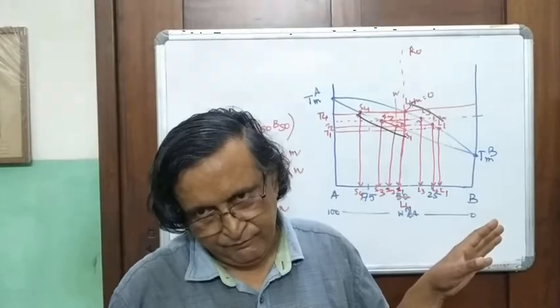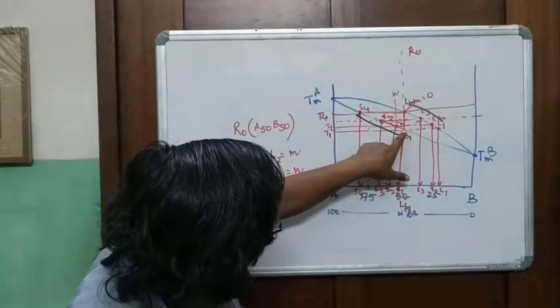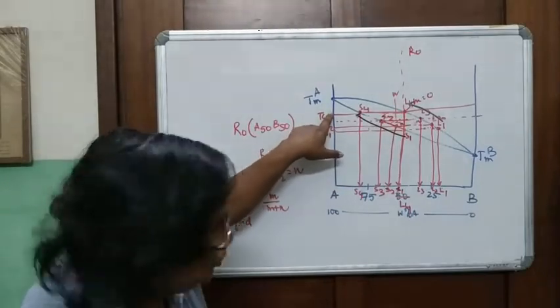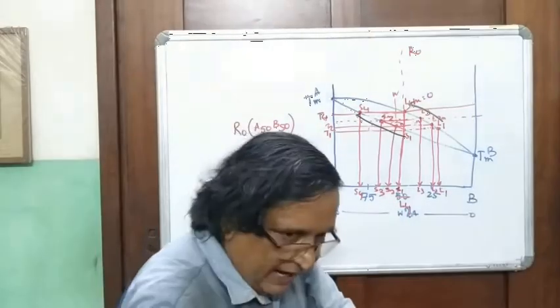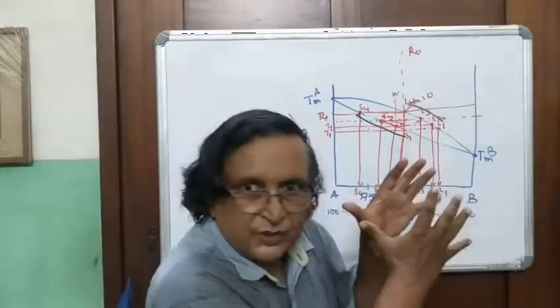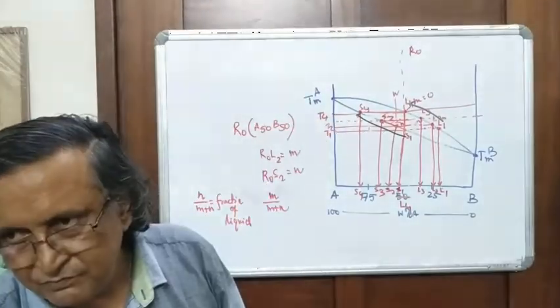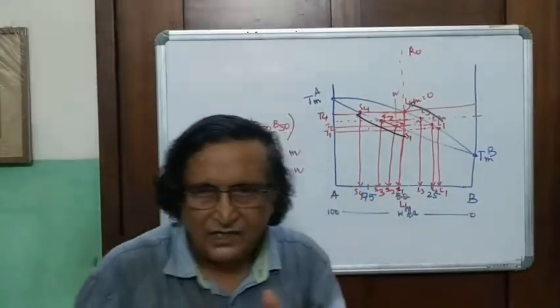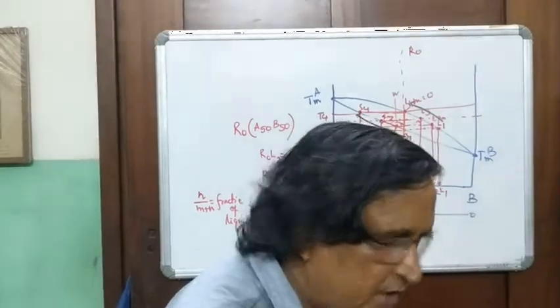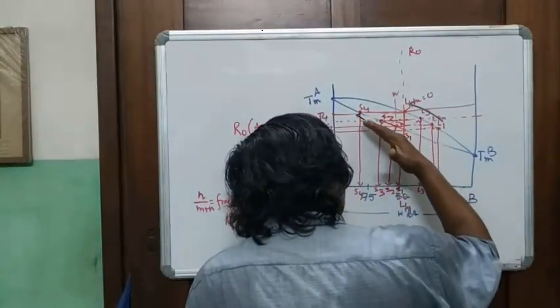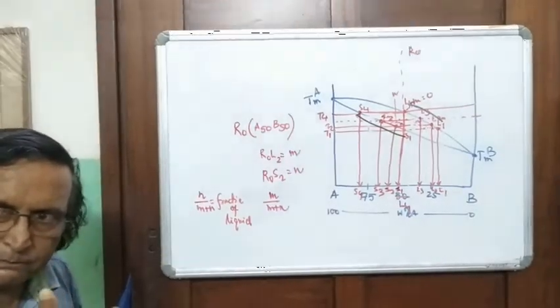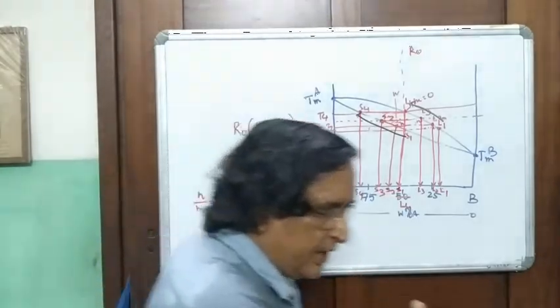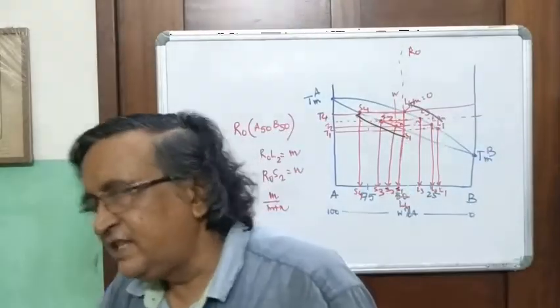And you see, S1 has a lower melting temperature than S4. So if you want to go on melting this to get from a pure rock to a pure melt, you have to supply heat to the system. There is not going to be any thermal buffering if you involve such a binary system. It is very important to realize that when you're melting solid solutions, the temperature needs to be continuously increased so that the rock is completely transferred to a melt. There is no question of thermal buffering, which was there during eutectic melting involving pure solid phases. This does not happen here.